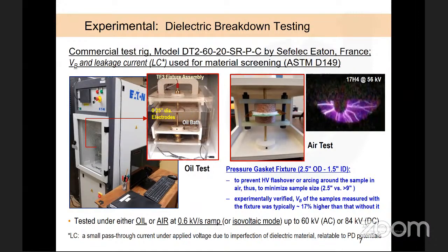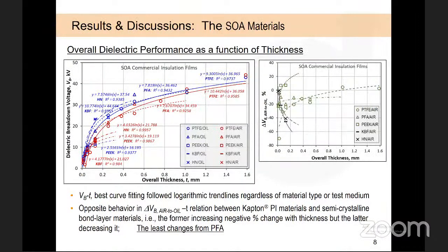So the pressure gasket fixture was designed based on ASTM suggestion. The test also measured the leakage current, a small pass-through current, even well before the breakdown, mainly due to imperfection of insulation material, thus relatable to partial discharge potentials. Now let's look at the test result.